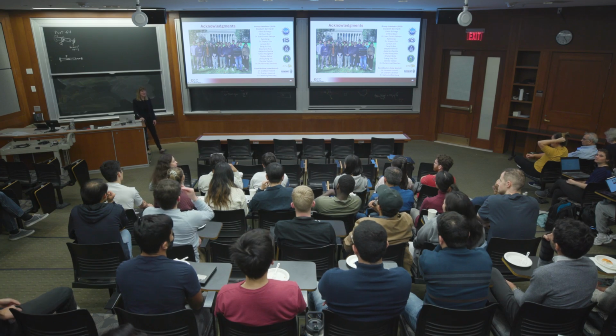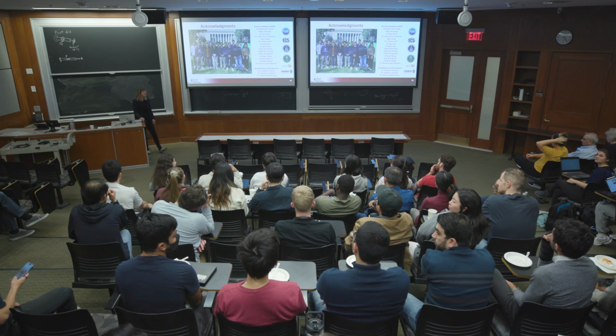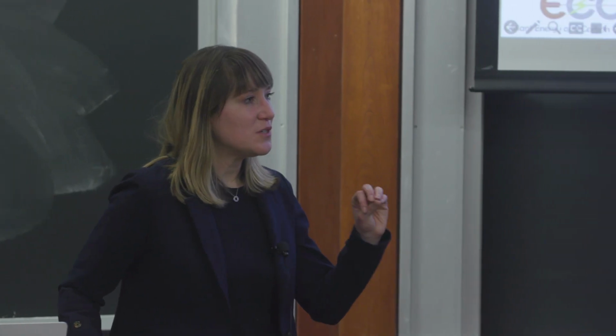Yeah, for the SEI. Well, we didn't look at them side by side in the same study. So sometimes electrolytes that tend to form CO2-derived phases in the SEI tend to be carbonate electrolytes, and they don't tend to have the highest performance. So definitionally, at least at the moment, they don't necessarily give us the highest Coulombic efficiency. And the highest Coulombic efficiency systems tend to have a lot of lithium oxide. So we haven't unified that picture yet.